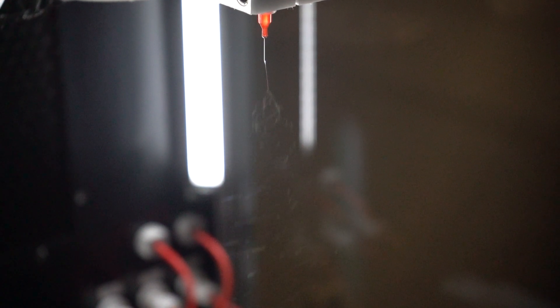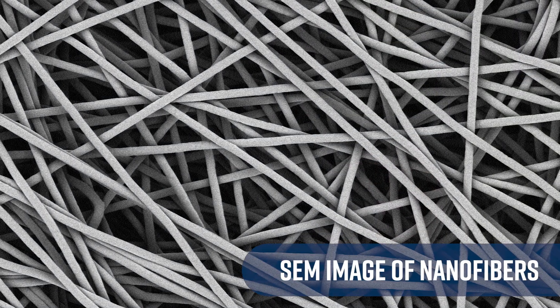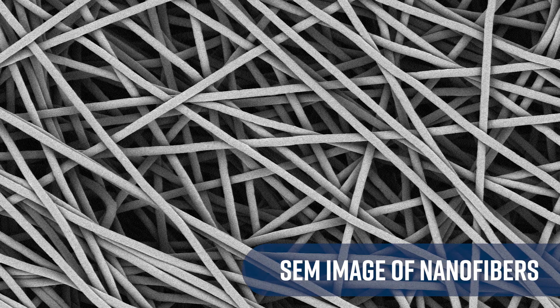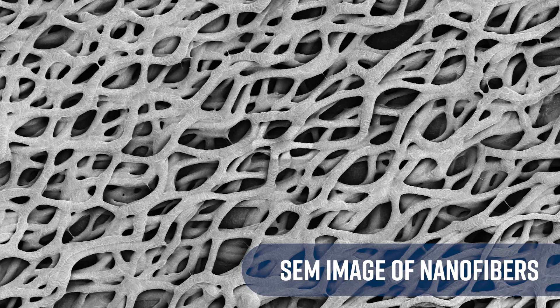Next, there's fiber control. The shape of the Taylor cone and the distance between the needle and collector influence the diameter of the resulting nanofibers. By controlling the Taylor cone, we can adjust characteristics of the fibers like its diameter and morphology. Then there's uniformity. The Taylor cone stability can be a great indication of the uniformity and consistency of nanofibers being produced. It can also give us an indication of certain electrospinning parameters that may need to be changed or optimized.